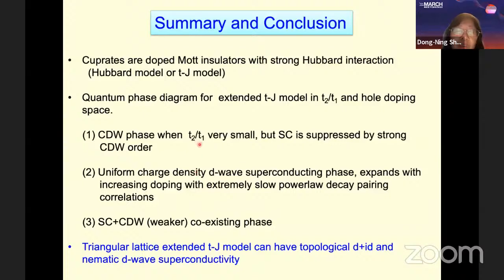Then with increased T2/T1, we get into a uniform charge density D-wave superconducting phase. That phase occupies larger space and expands in parameter space with increasing doping level. The superconducting pairing decays extremely slowly with a power law exponent much smaller than 1. Then we also have superconducting and CDW coexisting phase. Those are results for the square lattice TJ model.